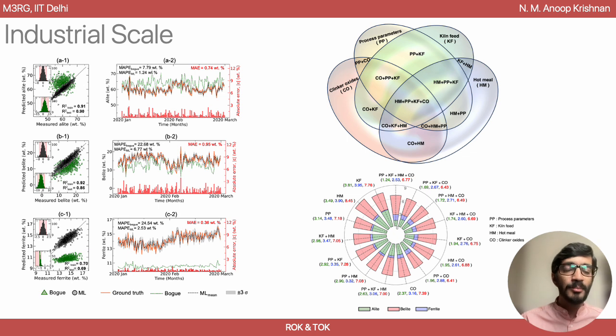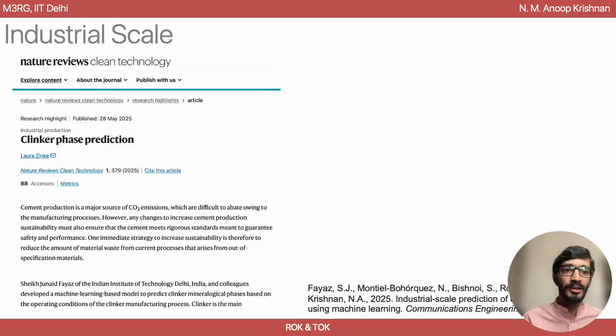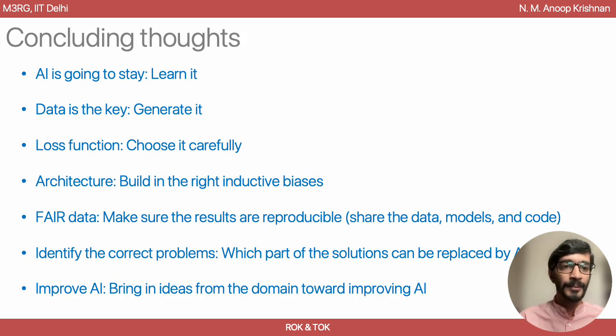The bottom line is that we are able to predict all three alite, belite and ferrite phases with high accuracy. Actually, we use random forest for this prediction. When you use it as a function of all these input features that I mentioned, we are also able to predict it accurately, for example, as a time series as well. So this work is already published, and interestingly, this work also got featured by Nature Reviews Clean Technology as part of a research highlight, which also highlights the importance of how such solutions can have an impact on industrial scale as well.